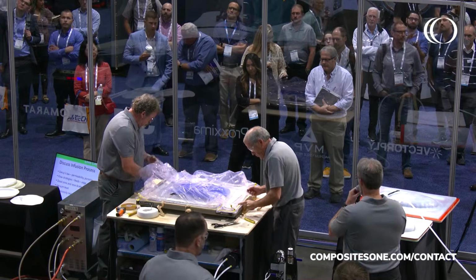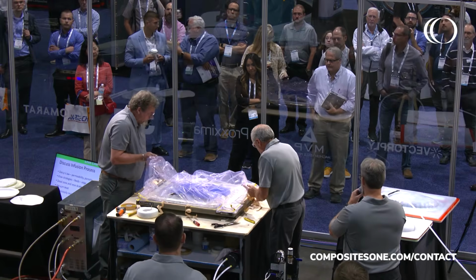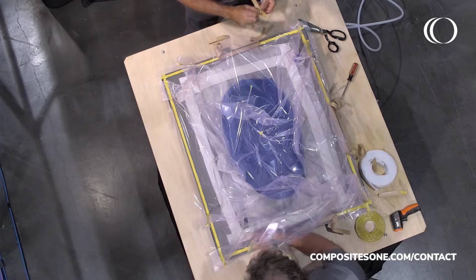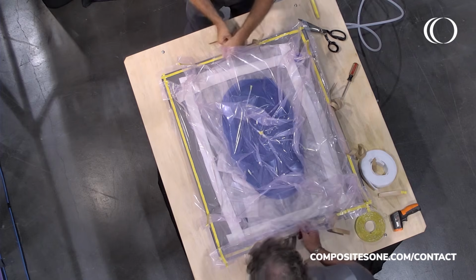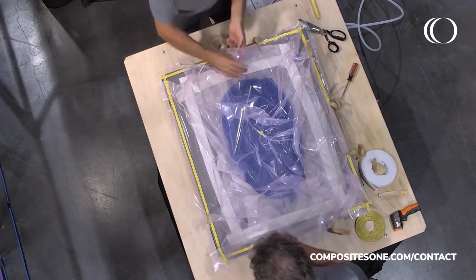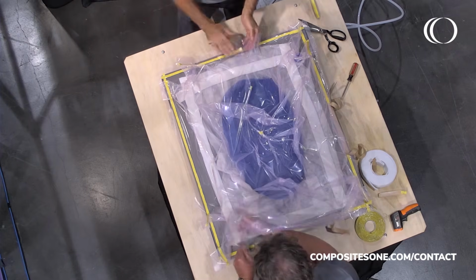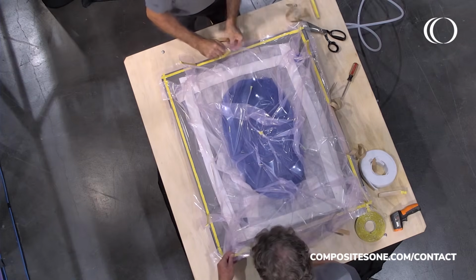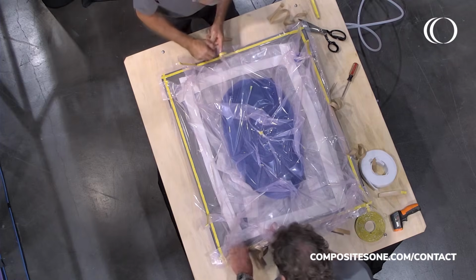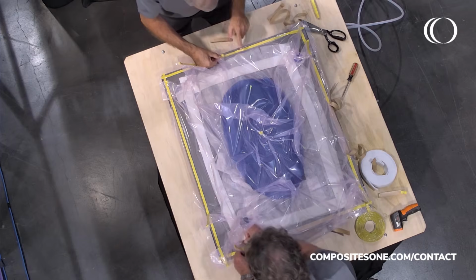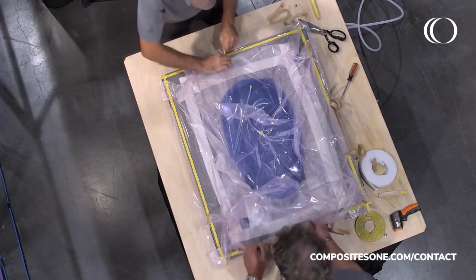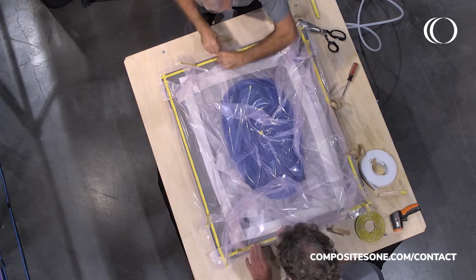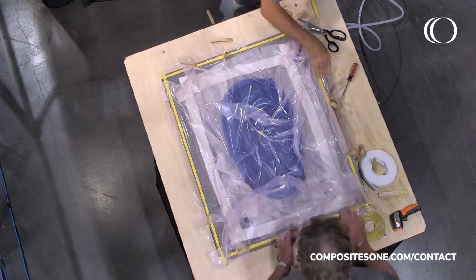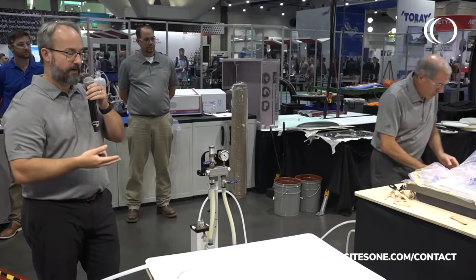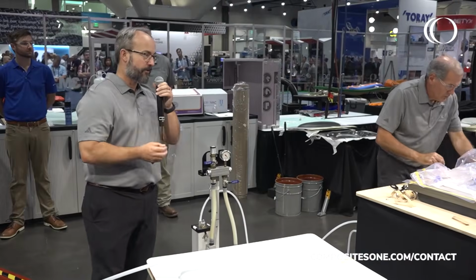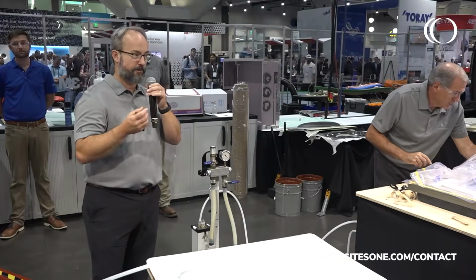The strategy they're using today is to pull vacuum around the perimeter. The white breather material on top of the peel ply is going to provide vacuum to the part. As Doug mentioned, we have the blue InfuPly material on top, and that's going to provide resin flow across the top of the part, and then the resin's going to permeate through the thickness of the part to the mold surface. We're going to introduce the resin in the very center of the part. We have a very small spiral wrap tubing to transfer the resin along the longitudinal axis of the part and into the InfuPly. Since the part is so small, we really want to control the flow, so we're using fairly small diameter lines to throttle the resin a little bit.